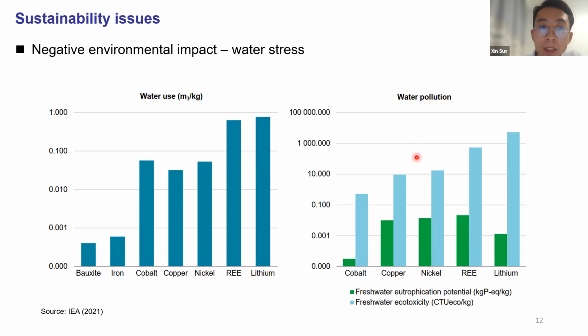So it's very bad. And also, these water use figures didn't take the water evaporation losses into account, because for lithium mining, you extract the lithium from the brine. And for the brine, you don't just use the water in the process. You also need to evaporate the water embodied in the brine, and it is lost into the natural environment. It's not recycled, so the water is lost. We just don't use it, but still it's a kind of loss.